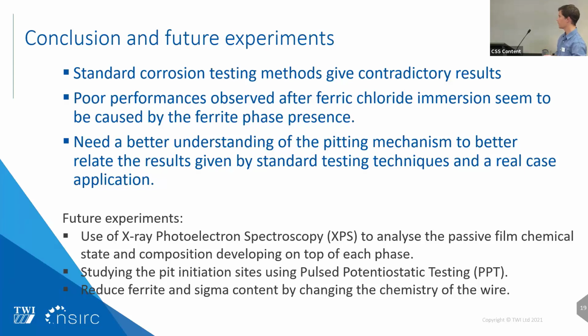Finally, we will try a new wire chemistry for the feeding stock. So far we have been using a conventional 316L welding wire, which results in a large amount of ferrite in it, as well as sigma, as I showed. This might also be a problem for the corrosion resistance. Sigma is introduced on purpose for welds because it limits the hot cracking effect within the weld, but in our case, if it hinders the corrosion resistance, we need to think about other chemistry that might be more relevant for corrosion resistance.